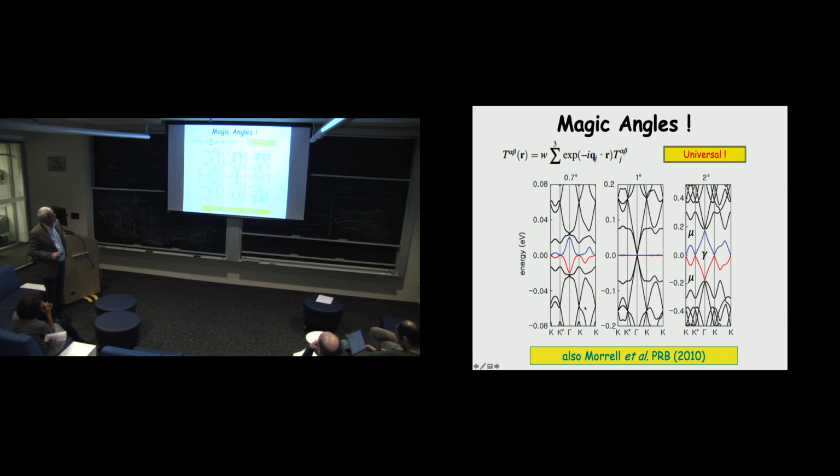And so here is the graphene version of the results that come from this kind of Moiré superlattice model for graphene. Let me talk about the right-hand side first. This is energy as a function of momentum, in what we call the Moiré-Brillouin zone, the Brillouin zone constructed from the periodicity of the Moiré superlattice. And this is a good quantum number in what we call this Moiré band model.